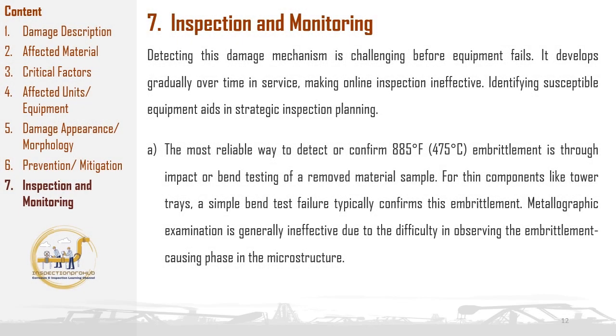In this last section, Section 7, we'll talk about inspection and monitoring of 885 degrees Fahrenheit embrittlement. Inspection and monitoring of 885 degrees Fahrenheit embrittlement present significant challenges due to the nature of this damage mechanism. Detecting this damage mechanism is challenging before equipment fails, as it develops gradually over time in service, making online inspection ineffective.